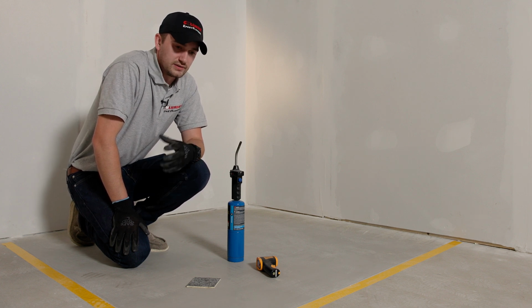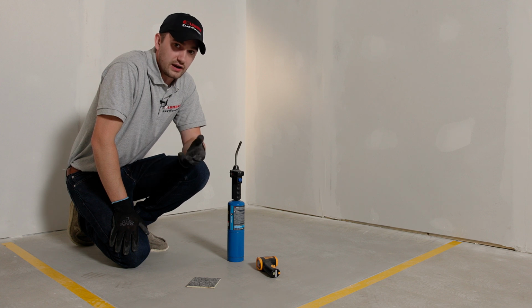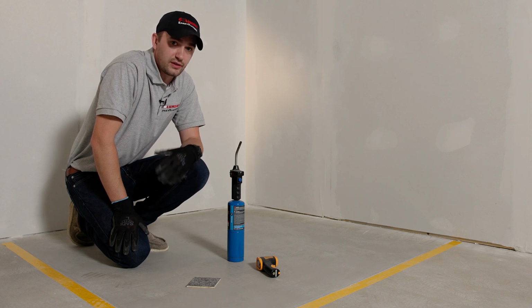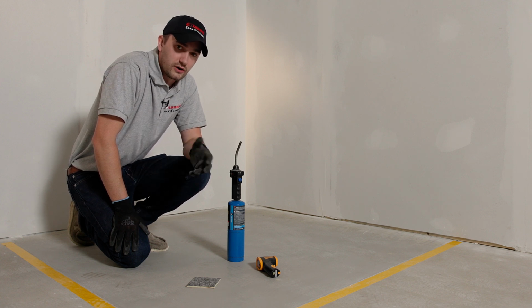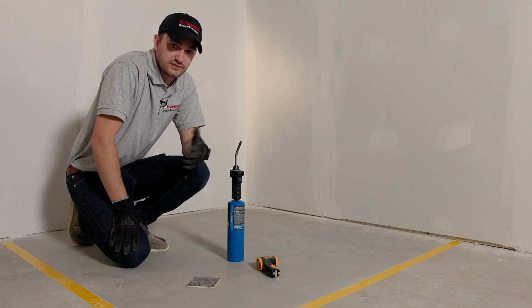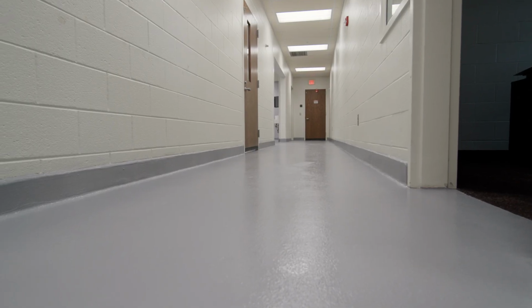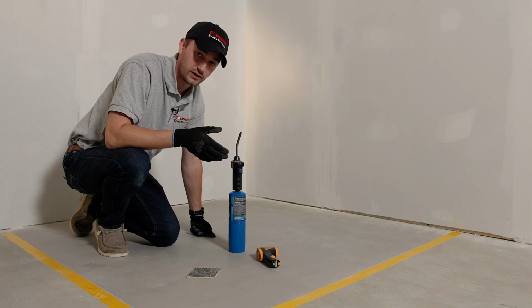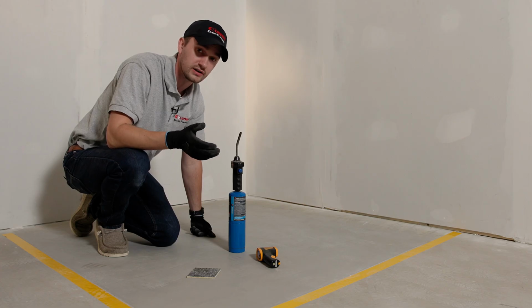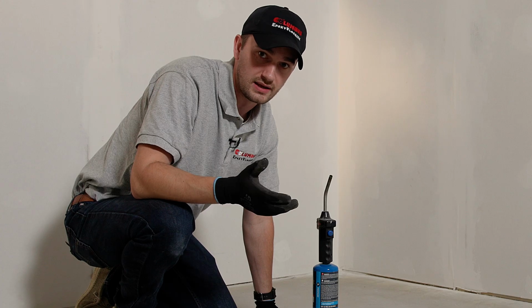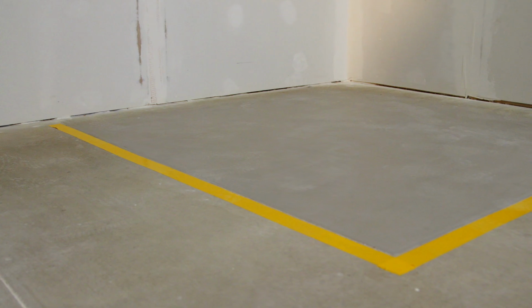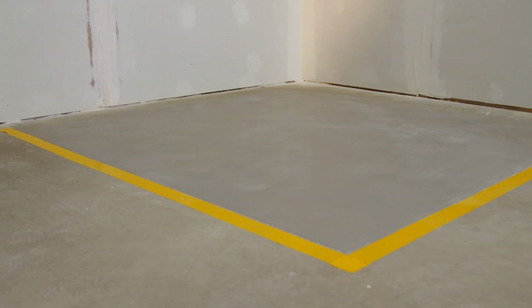We see them melt and deteriorate. It could be because of the fryers from the hot grease. It could be the thermal cycling from hot washdown areas by the freezers, just from that temperature fluctuation. The urethane cement is going to be able to hold up to and withstand all of that. For this floor, it can withstand from negative 100 degrees Fahrenheit up to 220 degrees Fahrenheit. Intermittent temperature, depending on the system that's installed, can go as high as up to 500 degrees Fahrenheit.